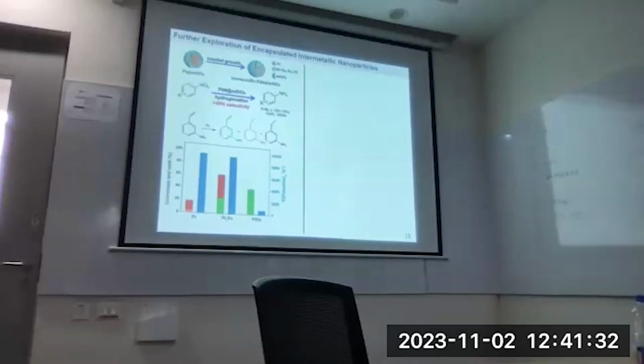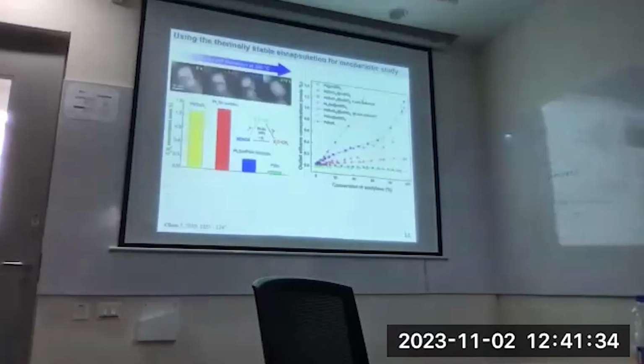What is the advantage of this encapsulation? For example, this reaction is happening at 200 degrees. Then we use this for propane dehydrogenation also, which happens at 650 degrees. At 650 degrees, I want to make sure my particles retain their integrity. They don't congeal and become bigger particles. When they become bigger, my activity drops. If it aggregates, it's gone.